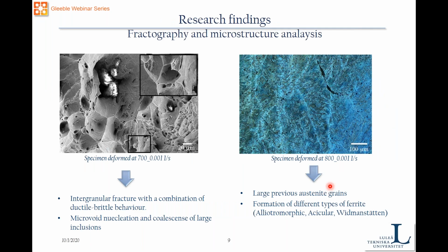The fractography and the microstructural analysis is telling us that we had important findings here, that we have a combination, actually in the left side, of ductile and brittle behavior in the material. So an intergranular fracture was found. But we also believe that the presence of inclusions is affecting the behavior of the material. So we have microvoid nucleation and coalescence of large inclusions.